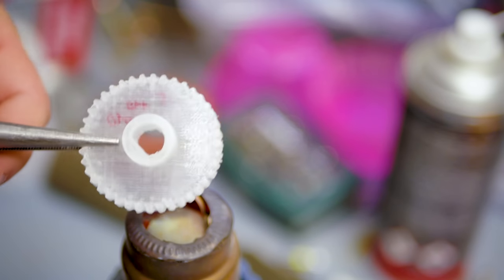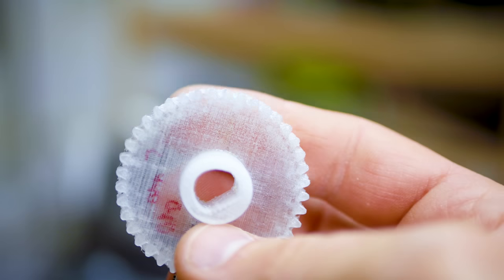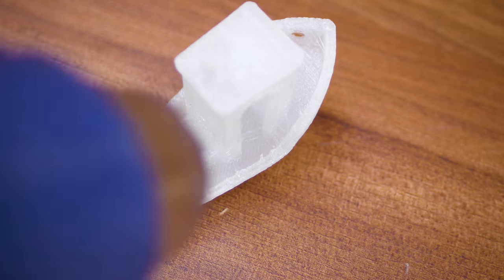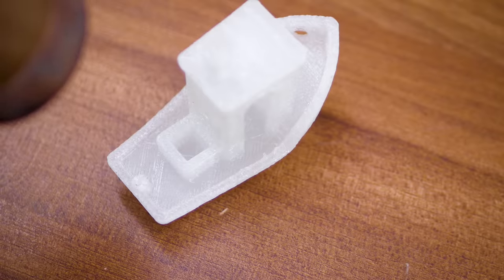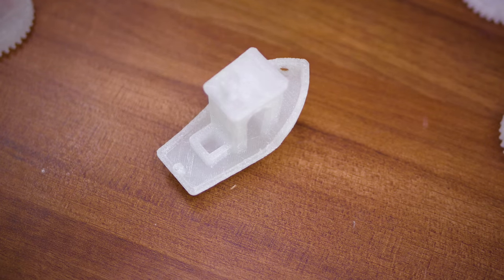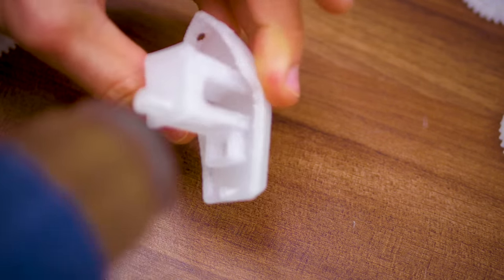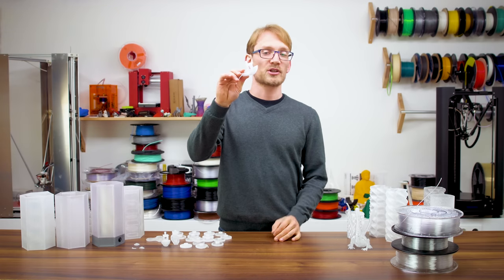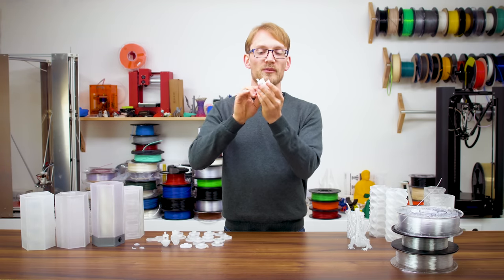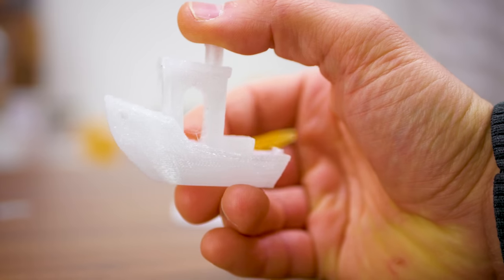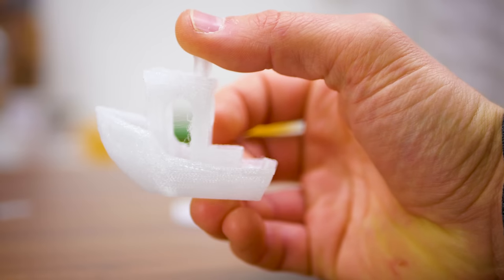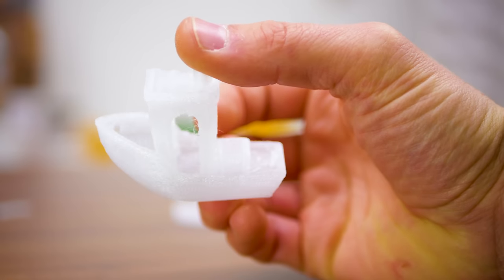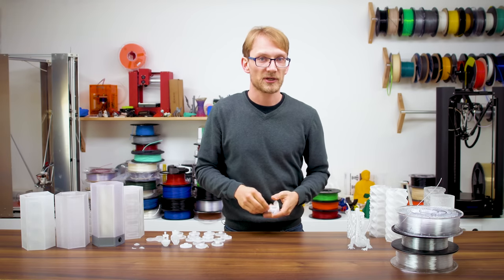But one nice thing you can do with heat, actually, for any filament, is to melt off these little hairs that PETG in particular likes to pull when the hotend moves from one area to the next. High heat and a single pass are usually enough to take care of them. And one last approach that didn't really work with the Benchy was the thicker layers at 300 micron. Even with the extrusion multiplier cranked up, it did not turn out transparent at all, though print quality overall was a bit more consistent compared to the low layer height parts.